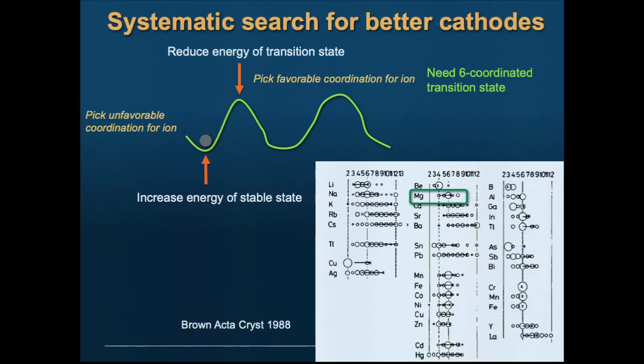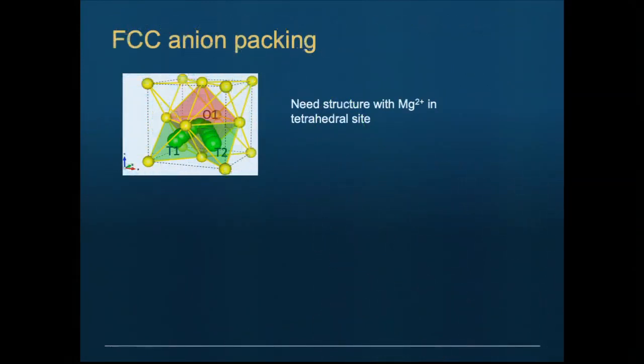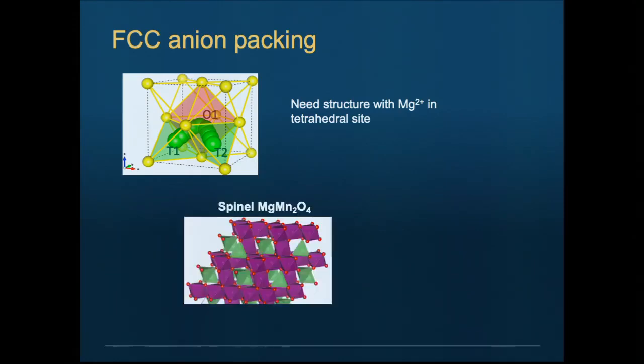Duh, for some old-style ceramists among you, that's a spinel, right? Because in spinel, you push one of the ions tetrahedral, even sometimes when it prefers to be octahedral. And because a spinel is an FCC oxygen packing, to diffuse from one tetrahedral site to the other, you have to go through the octahedral site. So this is perfect for magnesium, because magnesium prefers octahedral, but in spinel, it's pushed to tetrahedral. So it's going to sit in a slightly unhappy site, and then as it diffuses through, it becomes happier. So you get a chance to bring down the activated state.